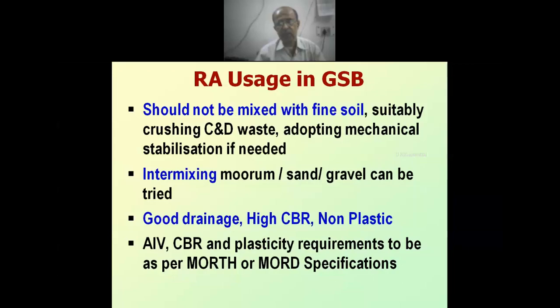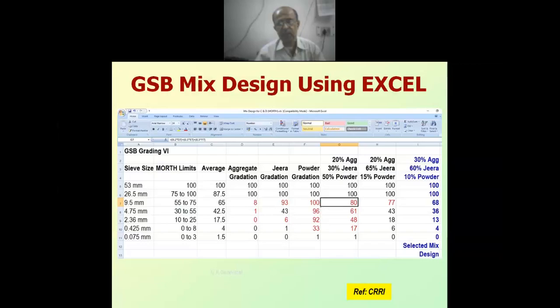Both MORD and MORTH specifications permit use of RA in the GSB layer, provided the aggregate impact value is less than 40%, the gradation limits are met, and it is non-plastic. This material is of course definitely non-plastic, unless, unfortunately, some clay material is intermixed with this C&D waste. It will not have any plasticity. It will be non-plastic, and its AIV value will usually be lesser than 40%. 40% is for the MORTH specification. If you follow the MORD rural road specification, the AIV limit is 50% for the sub-base layer and 40% for the base course layer. So C&D waste in the base course also you can definitely use as per the MORD specification for rural roads.